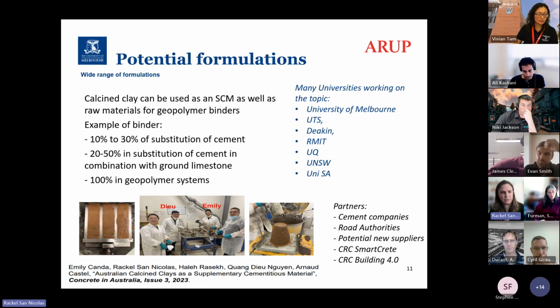You work with a range between 20 to 50% of substitution there. And we can go all the way to 100% of substitution of cement and have some kind of geopolymer system and different binders. Actually, a lot of the technology around geopolymers and alkali activated material was developed based on calcined clay products at the beginning, before moving on to slag and fly ash.